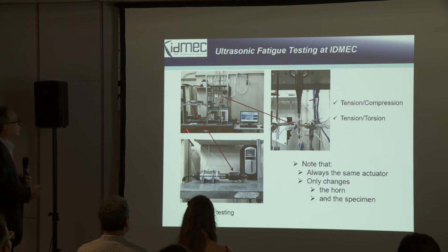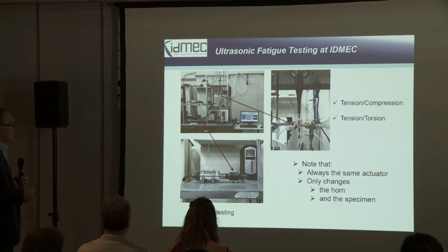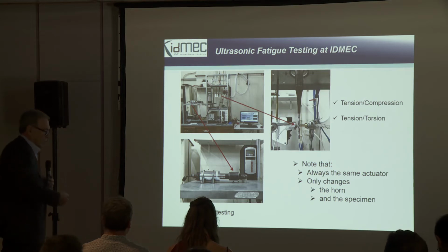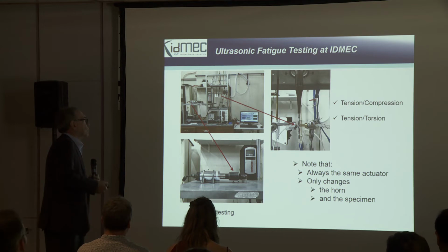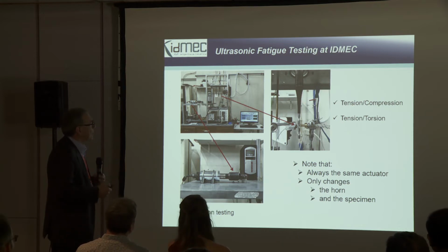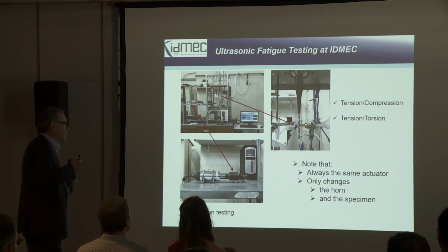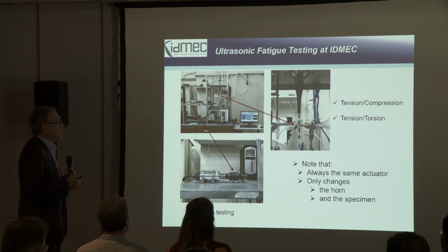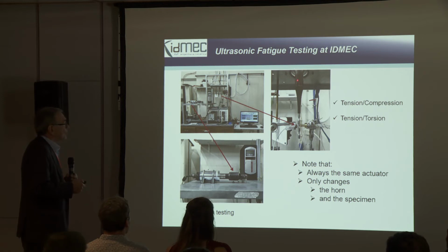So it seems complicated, but it's not complicated because the machine is only that and only that. All the rest is the standard gauge acquisition, temperature measurement, laser measurement, and controlling. So we have 2 machines here. This is our laboratory. We have 2 machines. And what is important in this is that we are testing either cruciform specimens, or torsion specimens, or uniaxial specimens, or tension-torsion specimens, always with the same piezoelectric actuator. We only change the horn and the specimen.